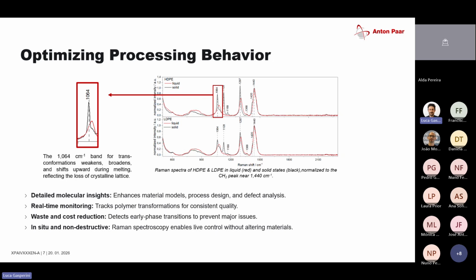And again, we're looking for a peak that drastically changes during melting. So we came across this peak here, which is perfect because it's a very distinct peak. But if I go into the melting phase, the peak gets much lower, broader, and moves a little bit to the right. So there's a lot of signal changing here. By just looking at this peak, I can actually tell how high the crystallinity is, or how amorphous a sample is. If you combine this, for example, with a DSC measurement, you can also get an idea of the percent crystallinity during the rheological analysis.